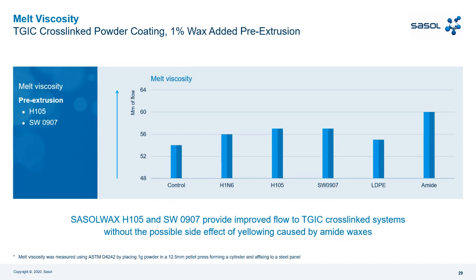And then follows the amide. Amide in this case gives the best results for the test with respect to the control, but as you can see in the words below the test, Sasol Wax H105, the Fischer-Tropsch, and the Sasol Wax 0907, the microcrystalline one, they can achieve a melt viscosity, but without possible yellowish in the final formula. So this is important for you. This test was done in pre-extrusion.